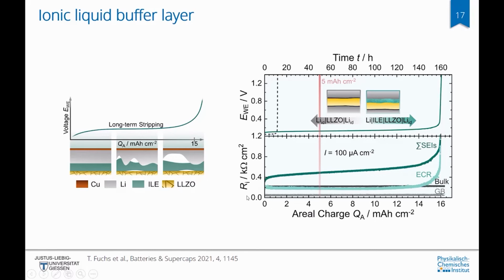And just to show the comparison here, on the left, this dashed line shows the cell with ideal lithium electrodes without ionic liquid interlayer, and the green line shows how much the stripping can be extended before the overpotential increases. And with these results, we have a strong indication that hybrid systems will play a big role in future.